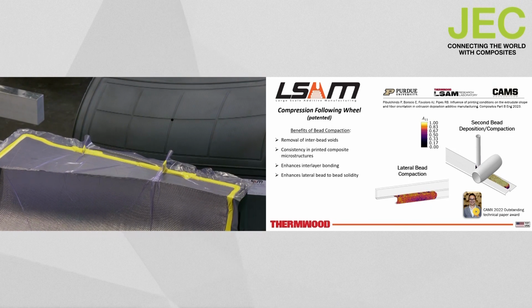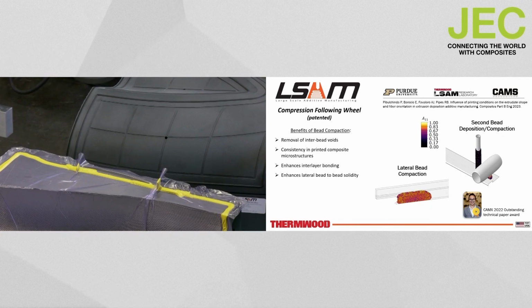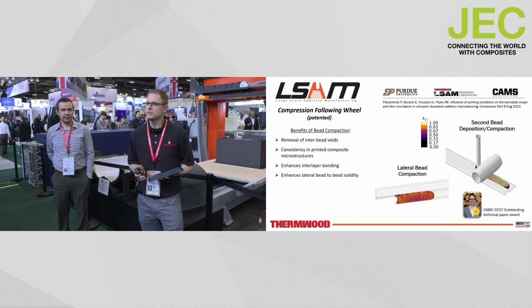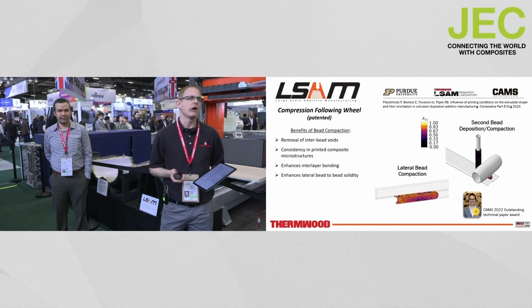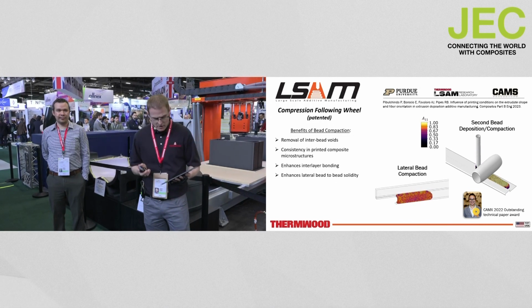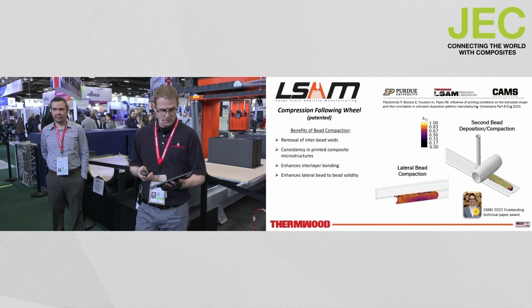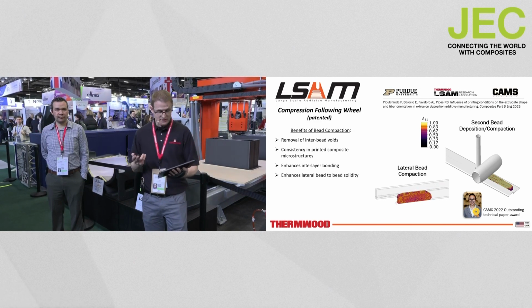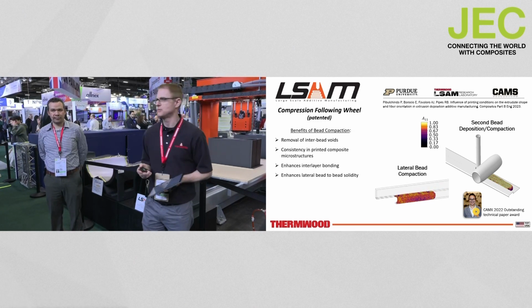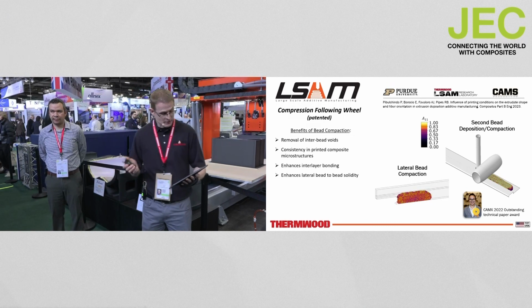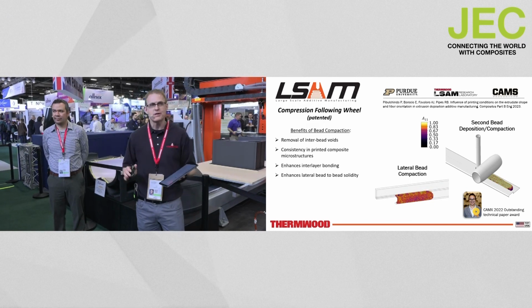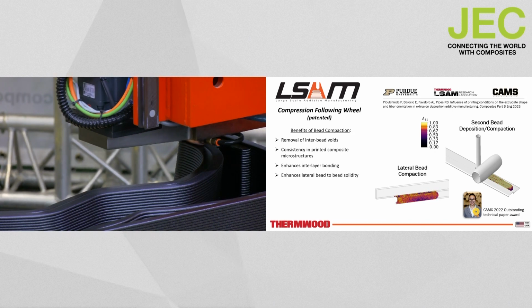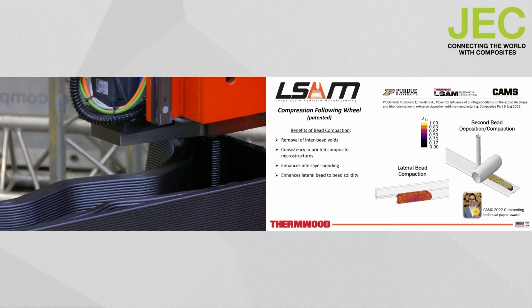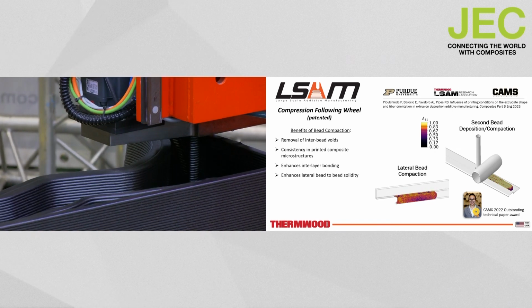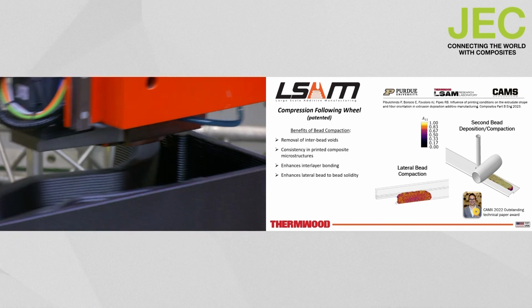In fact, a study performed by a group at the LSAM Research Laboratory further emphasizes the benefits of this active compaction. Bead compaction aids in the removal of interbead voids. It improves consistency in the printed composite microstructure, which includes repeatable fiber orientation. It enhances interlayer bonding and provides the best results for lateral bead-to-bead solidity.